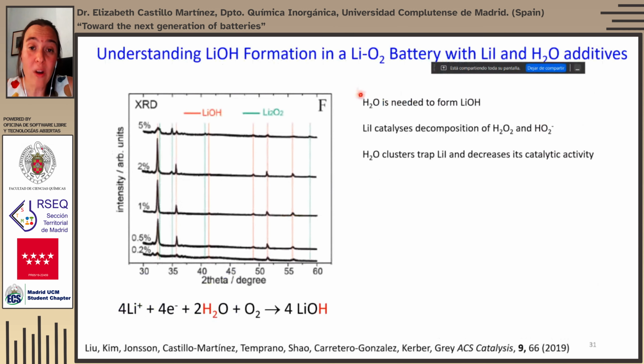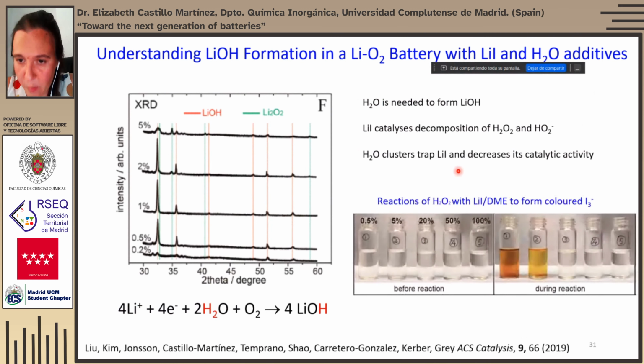Interestingly, water is needed to form lithium hydroxide, but the lithium iodide is also needed to form lithium hydroxide, because lithium iodide catalyzes the decomposition of the peroxide species. And in the absence of lithium iodide, it is lithium peroxide that forms. However, if there is lots of water, the water cluster traps the lithium iodide, and then it decreases its catalytic activity. So there is an optimum range, an optimum water content that can be put into the electrolyte to have the desired lithium hydroxide reactivity with proper reversibility.